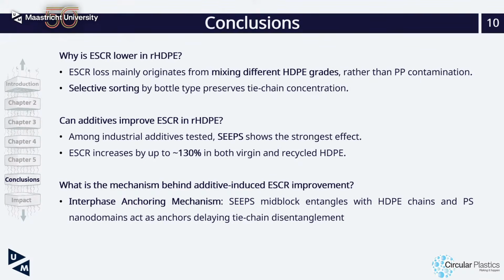Second, among different additives that we tested, we found the styrenic block copolymer that showed improvement in both virgin and recyclate grades of HDPE, about up to 130%. We propose interface anchoring mechanism to explain why ESCR improves when we add this additive.